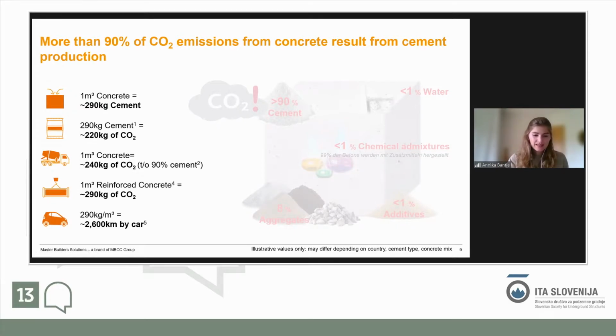And just the basics, basically. Before we do that, I quickly want to give you an example just to put everything into perspective. We have 1 cubic meter of concrete, which contains 290 kg of cement in a normal ready mix type concrete. Then we can check, okay, with the CEM2A, for example, we would have a carbon footprint of 220 kg of CO2. Adding up everything else that goes into it, with 90% originating from cement, we have a footprint for this 1 cubic meter of concrete of 240 kg, and adding the reinforcement it will be 290 kg of CO2.